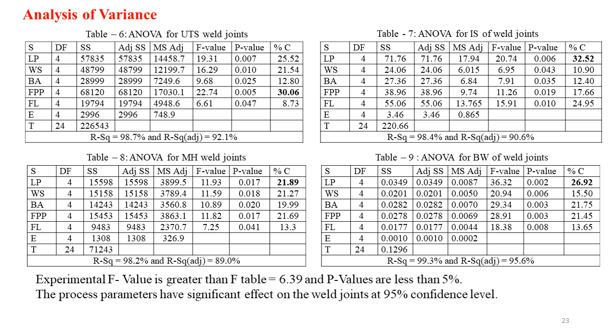The most influential factor for UTS is focal point position, for impact strength it is laser power, for micro hardness it is laser power, and for bead width, laser power is the most influential factor. Laser power, welding speed, beam angle, focal point position, and focal length are significant parameters in UTS as well as impact strength. According to the tabulated p values, all the p values are less than 5%, and the F table values are also greater than 6.39. That's why those are significant parameters.